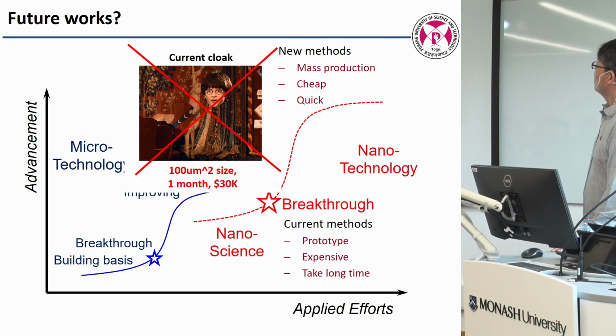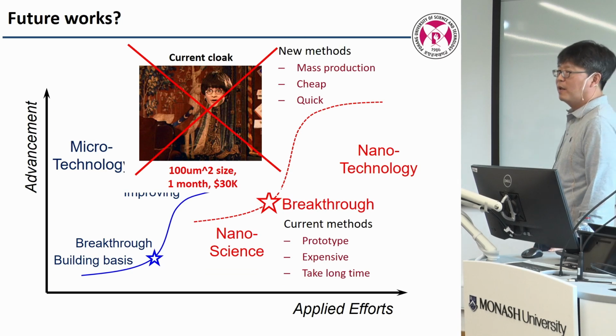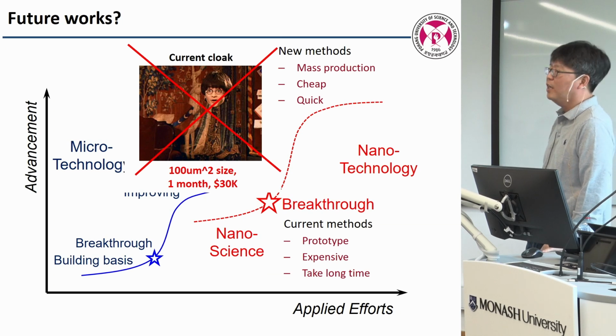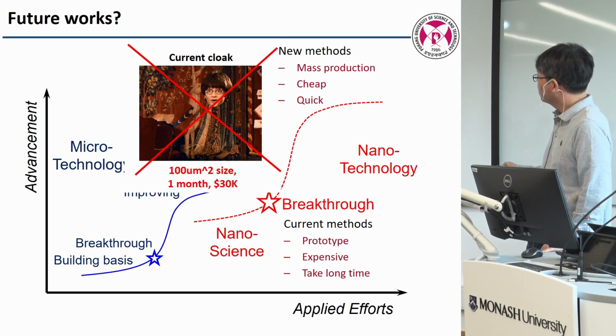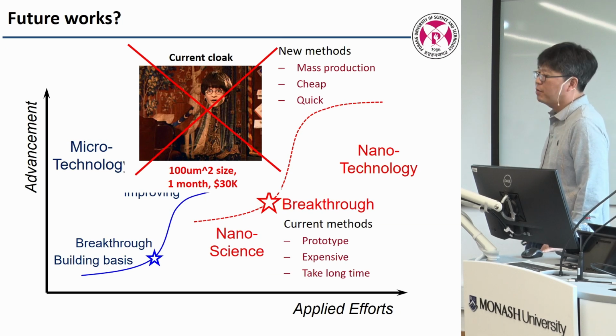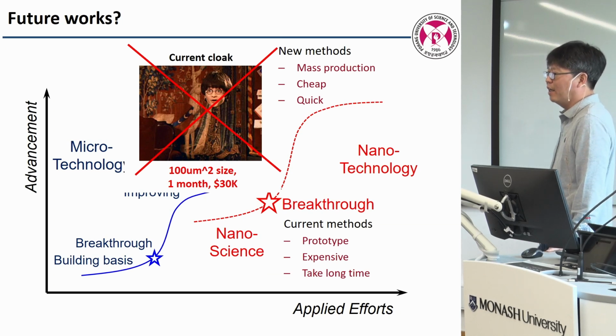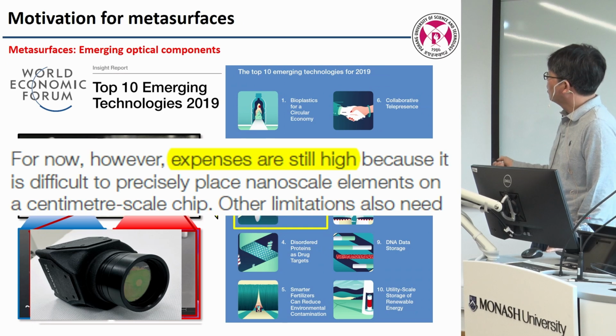But the problem, okay, is that all the beautiful work is fabricated in a very small area because mostly we use e-beam lithography. So it is not good for mass manufacturing; it's a prototype, expensive, and repeatability is bad. So what we need is mass production that is reliable, repeatable, high yield, and so on. Indeed, this Davos forum commented, okay, this is good technology, but the expenses are very high.